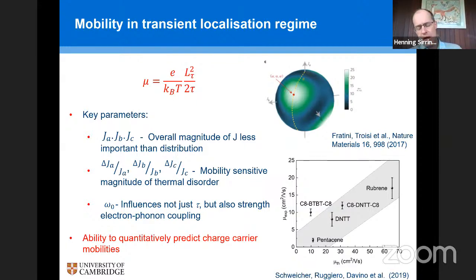You also need to worry, of course, about how large these thermal disorder effects are. You want the fluctuations of transfer integrals to be as small as possible, relative to the size of the transfer integral itself. And then the mobility also depends on the characteristic molecular vibration frequency. You want these to be as stiff as possible. And if you can compute all these quantities in the right way, then you can relatively quantitatively predict charge carrier mobilities. You can see that in the plot here on the right-hand side. There is a fairly good correlation between the theoretically predicted mobility within this framework and the experimentally observed mobility in single crystals.